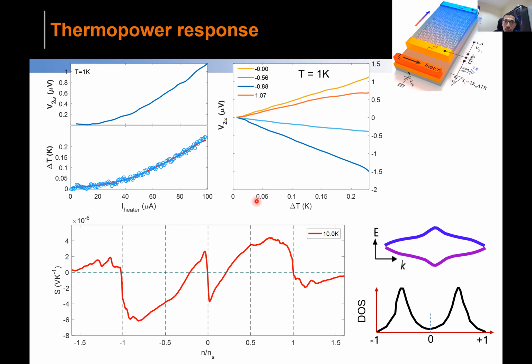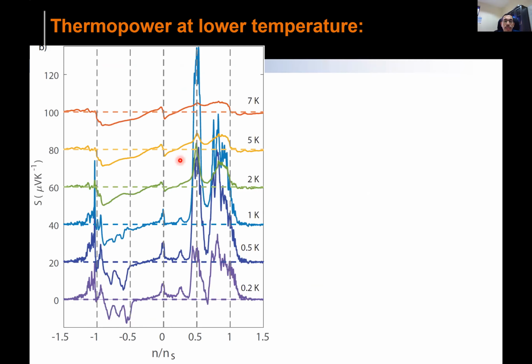So then the slope of each curve is plotted here. Which means that at every point we have this data as a function of density. And then we plot the slope of each curve, which gives the Seebeck curve. Okay, so now let's see what happens if I cool down. There is a dramatic thing happening.